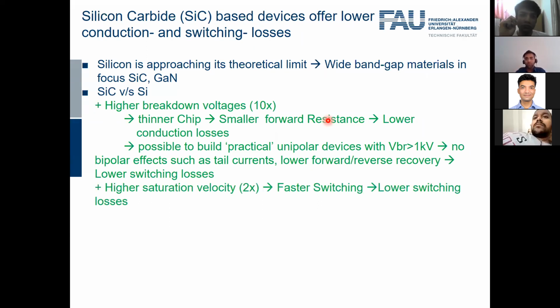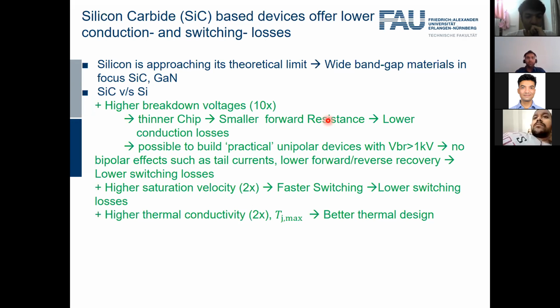And the third thing is, of course, silicon carbide has a higher drift saturation velocity, which means it can switch faster compared to silicon. And of course, this also has an impact on the switching losses. And one often discussed topic in literature is that silicon carbide has a higher thermal conductivity, which is true. Silicon carbide has 2 times the thermal conductivity of silicon, and therefore it can enable a better thermal design. Of course, this is true on paper, but in reality, this does not help much because in today's world, the silicon devices are anyways very thin. So the devices themselves don't contribute too much to the thermal conductivity.